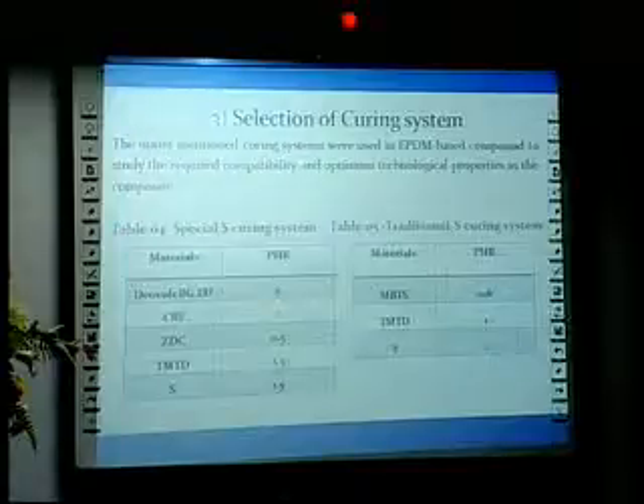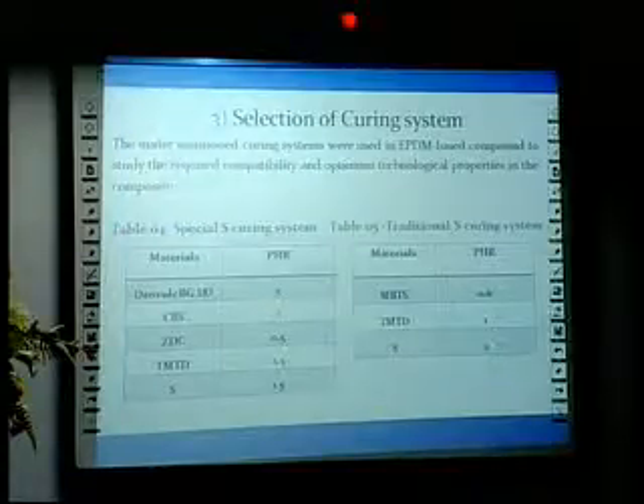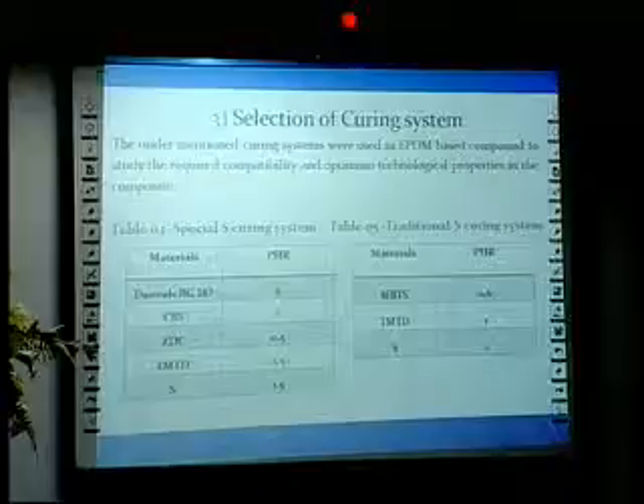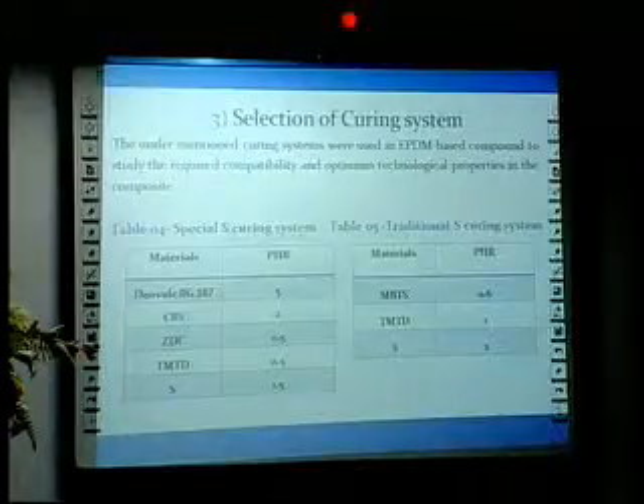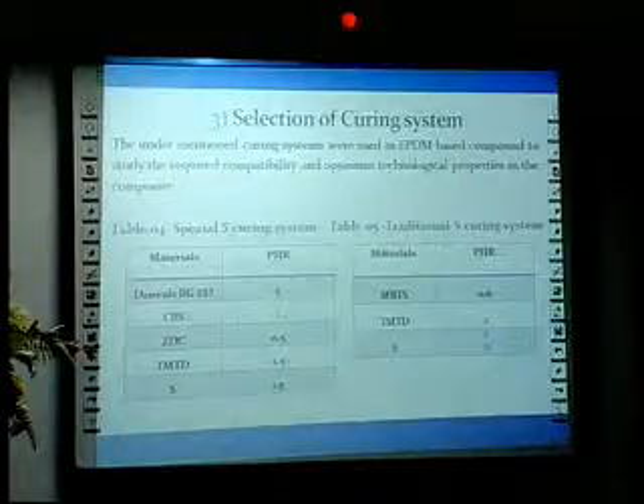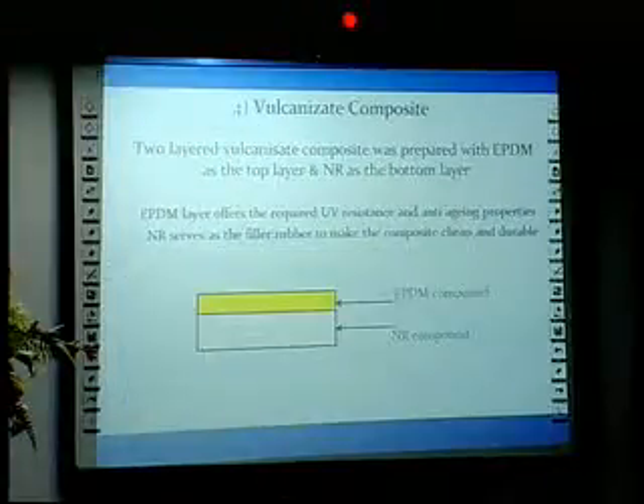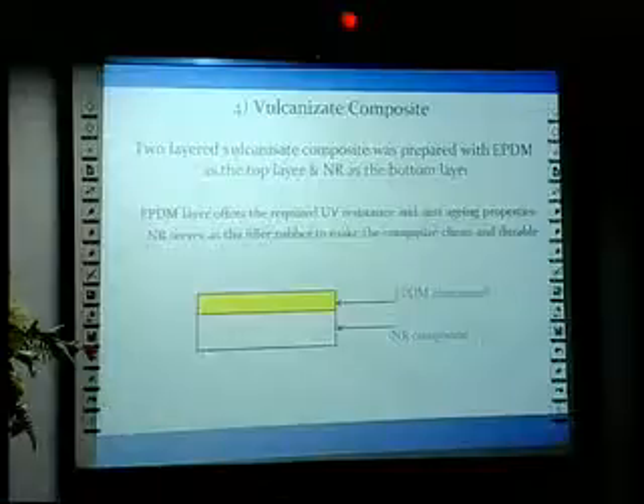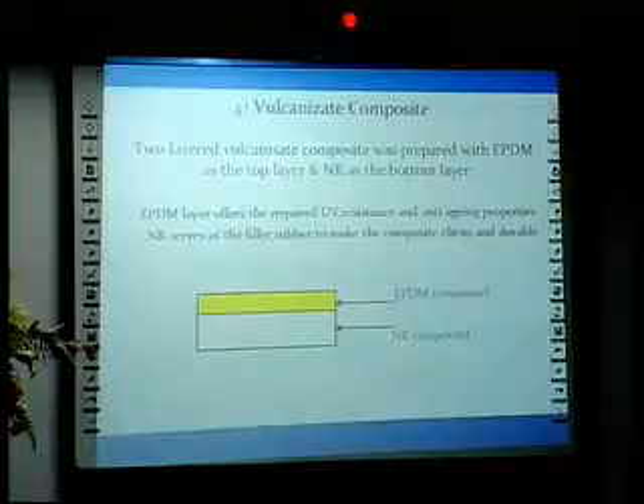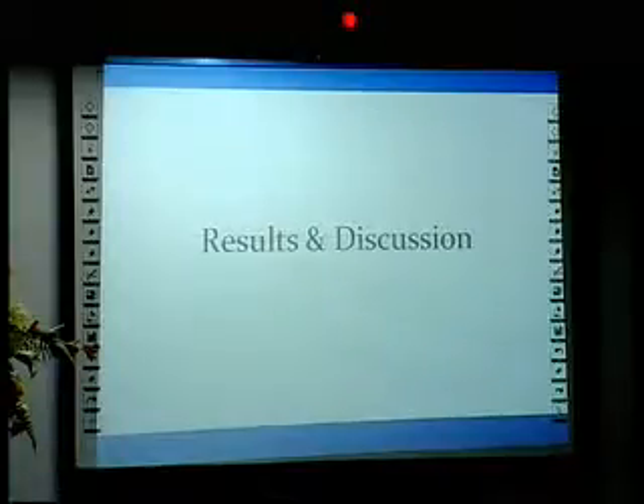Table 4 and Table 5 show the materials used in the special sulfur curing system and the traditional sulfur curing system. As the final part of the experiment, we developed the vulcanizate compound as a two-layered compound with the EPDM-based rubber and the natural rubber-based compound. Then we move to the results and discussions.